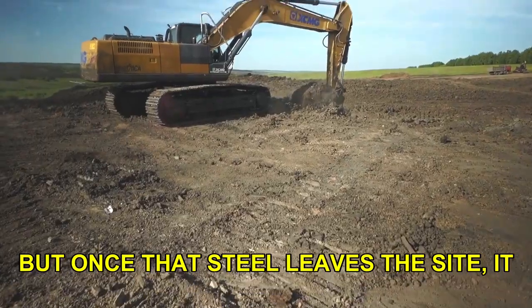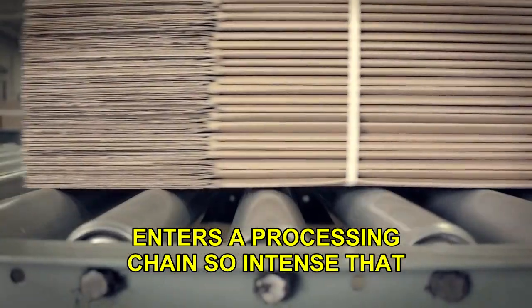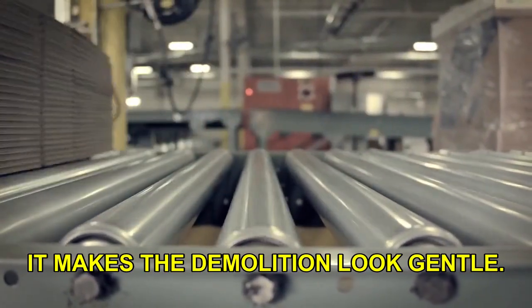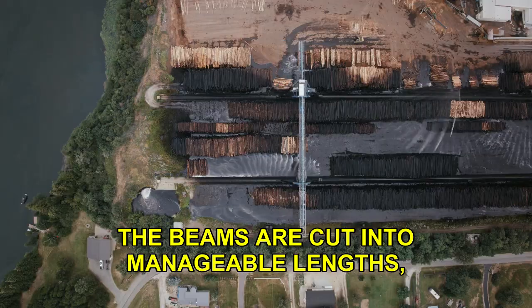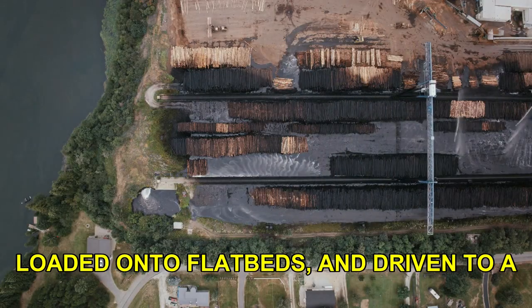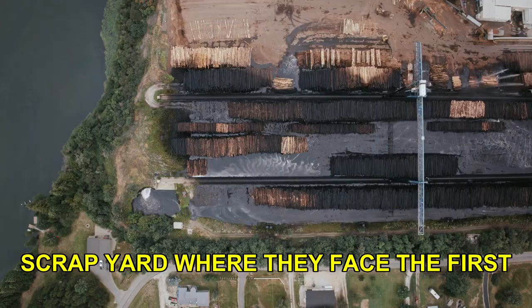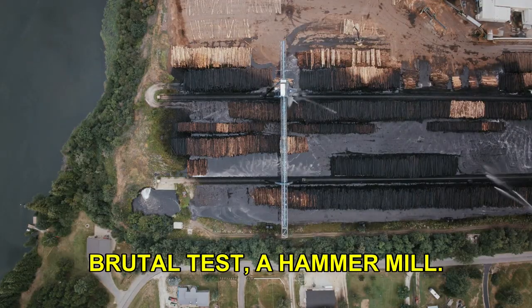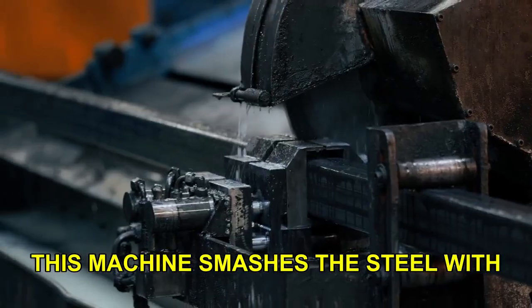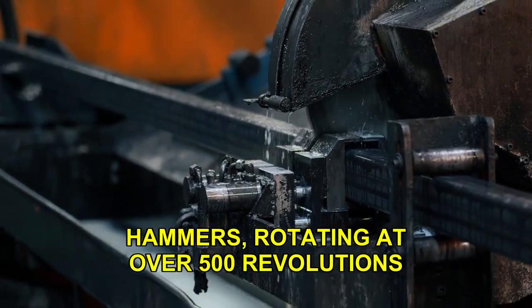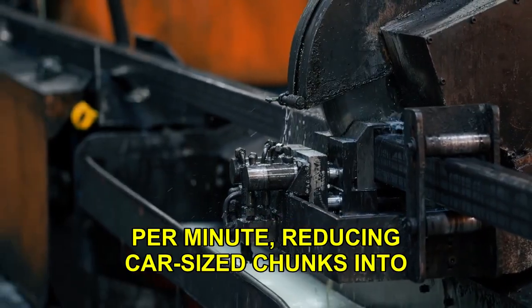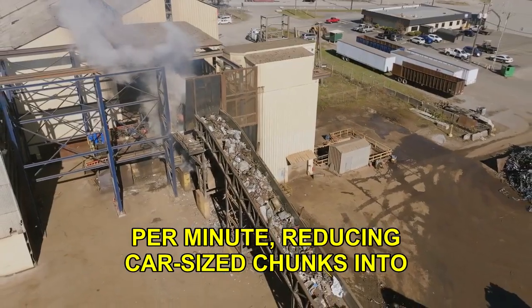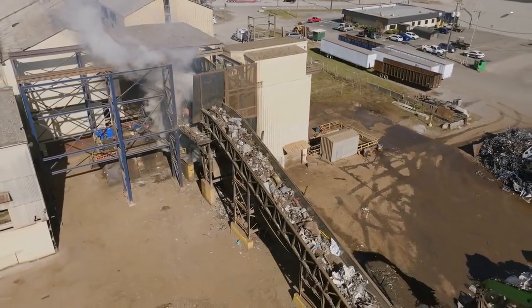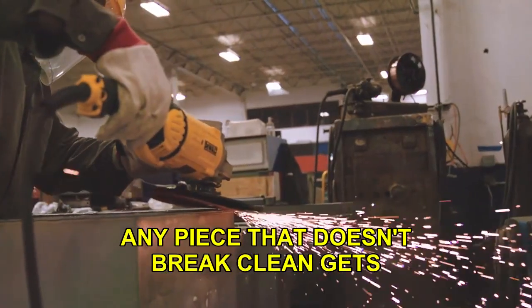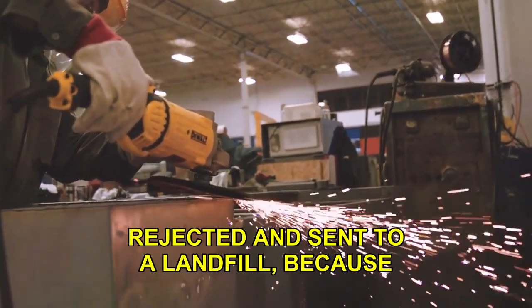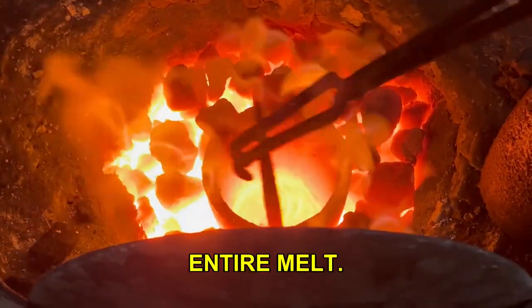But once that steel leaves the site, it enters a processing chain so intense that it makes the demolition look gentle. The beams are cut into manageable lengths, loaded onto flatbeds, and driven to a scrap yard where they face the first brutal test: a hammer mill. This machine smashes the steel with hammers, rotating at over 500 revolutions per minute, reducing car-sized chunks into hand-sized shreds in seconds. Any piece that doesn't break clean gets rejected and sent to a landfill, because impurities in the furnace can ruin an entire melt.